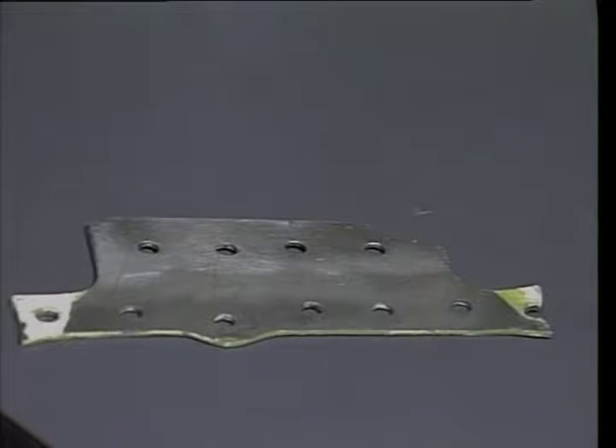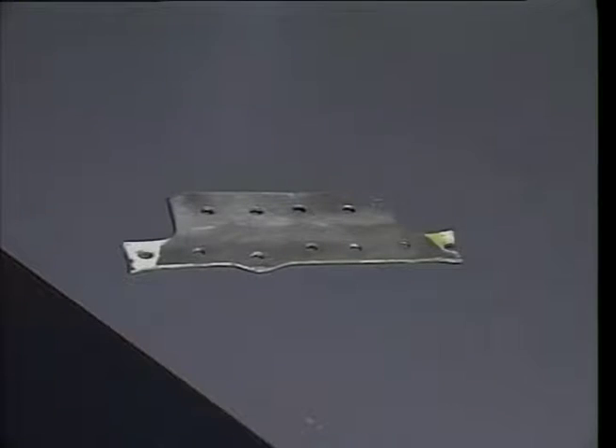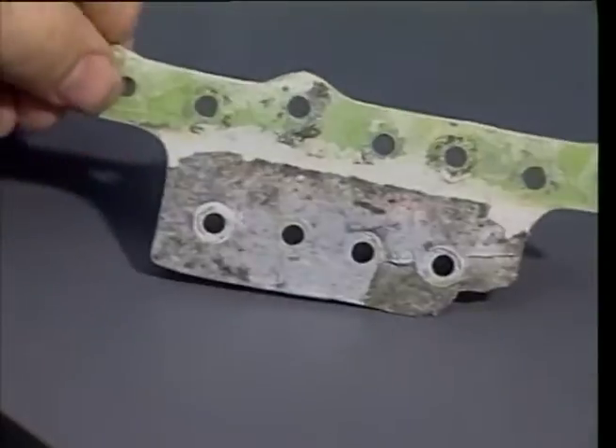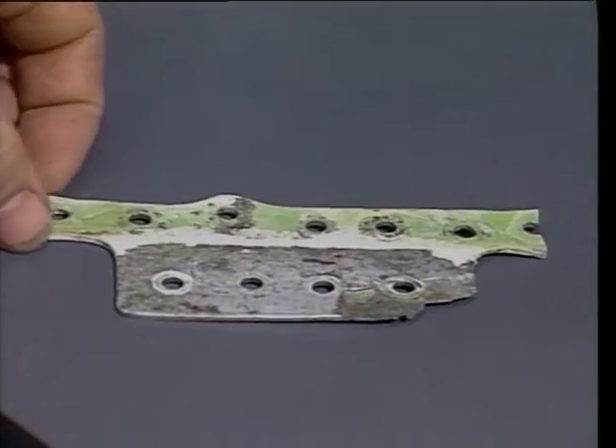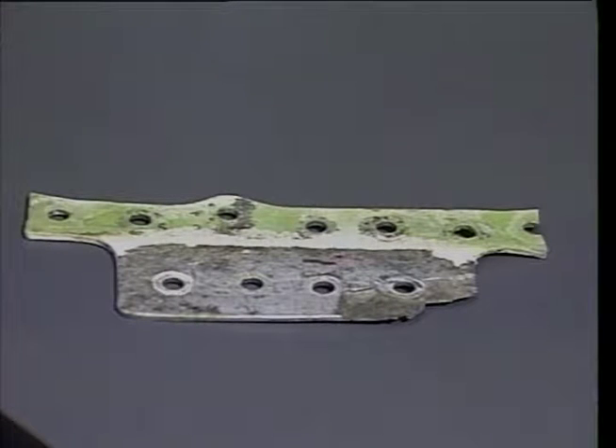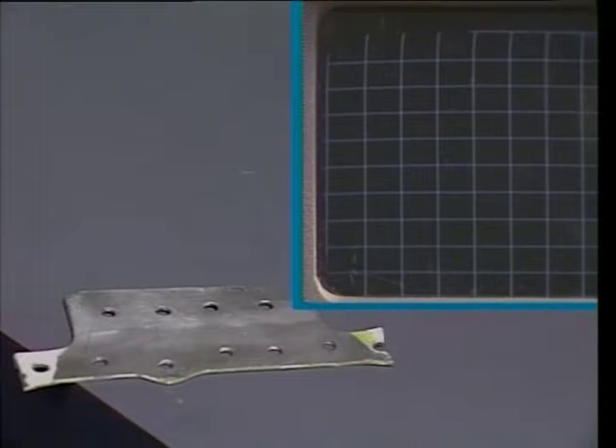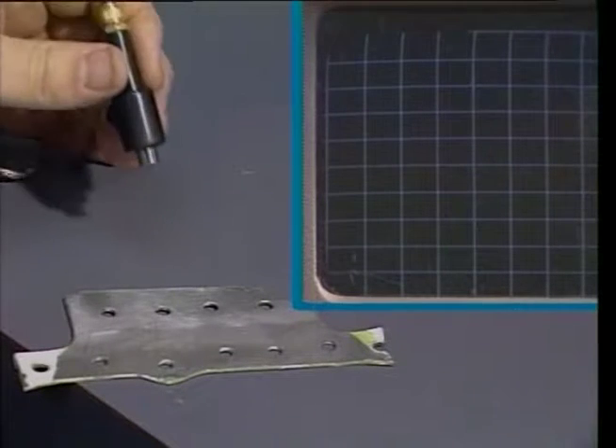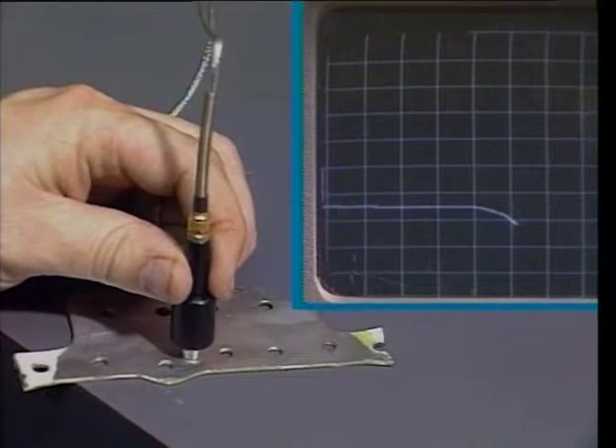This sample piece of aluminum skin was removed from the fuselage of a jet transport. The exterior surface has already been ground smooth, but the interior reveals an area of severe thickness loss due to corrosion. This split screen demonstrates the sensitivity of low-frequency eddy current technique in the hands of a skilled technician.